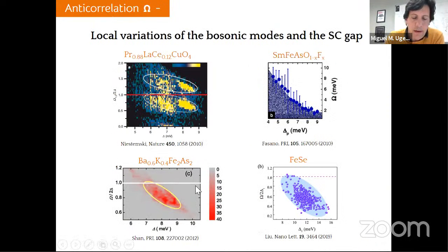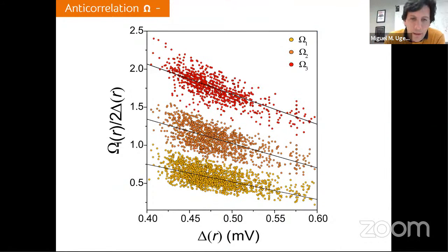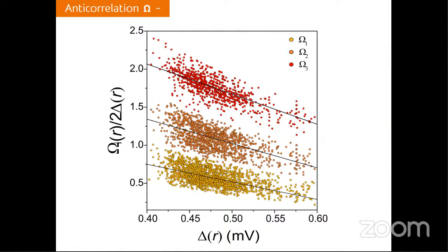So in all these works, this relation has been proved, as I said, using local variations, inhomogeneities of the superconducting order parameter. And this is something that we also tried to study in our system, and here is the result. Here you can see the evolution of the fundamental mode, the first harmonic and the second harmonic for all of the omega values, or all the superconducting gap values that we have. So we have used all the curves that we previously showed you for the histogram. So here's a bunch of them. And in general, all of them show a clear anticorrelation.